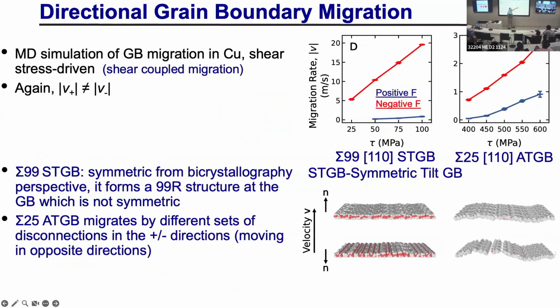Okay, so these are grain boundaries driven by an applied shear stress. And you can see much different mobilities in two directions. And this boundary is kind of a weird one. I'll tell you why in just a minute. But this one, basically, the way it moves is by moving sets of disconnections, but different ones in the two directions. This is an asymmetric tilt boundary. This one's a symmetric tilt grain boundary. Now, it seems to have different mobilities in the different directions, even though it's symmetric.